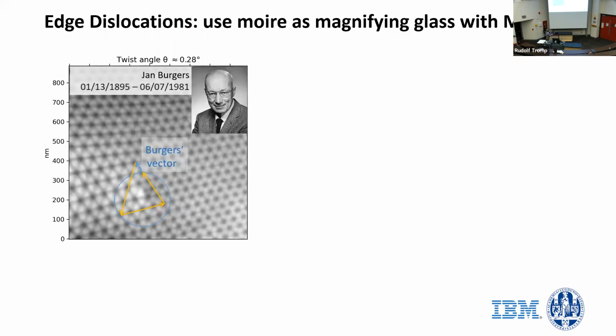We can draw a Burgers circuit. This is Jan Burgers, who was a professor at Delft University. So we go 1, 2, 3, 4, 1, 2, 3, 4, 1, 2, 3, 4, and there's a missing piece. That's the Burgers vector, right? And you see it's big. This is nanometers, so this Burgers vector is about 5 nanometers on the Moiré lattice. How is that related to the atomic scale Burgers vector? Well,